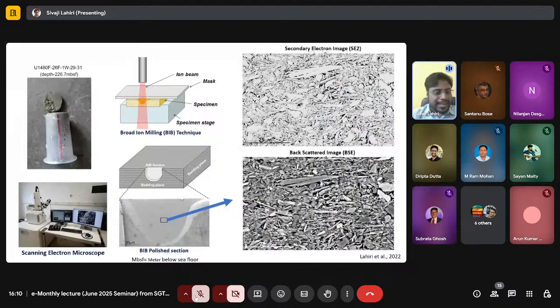So first, we collected samples from IODP. This is the typical sample. You can observe that we have received from IODP. Thereafter, we tried to polish the sample using broad ion milling technique. Now, utilizing this technique, we can prepare very smooth, polished sample surfaces.